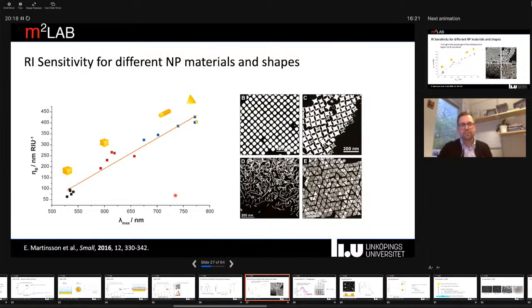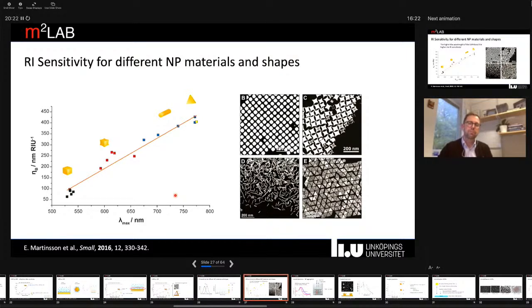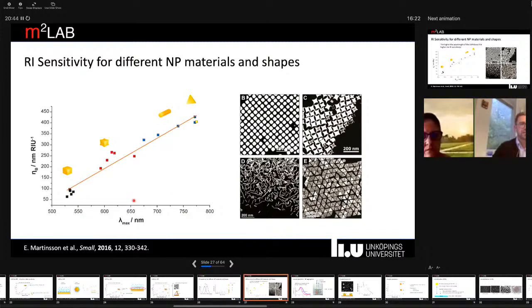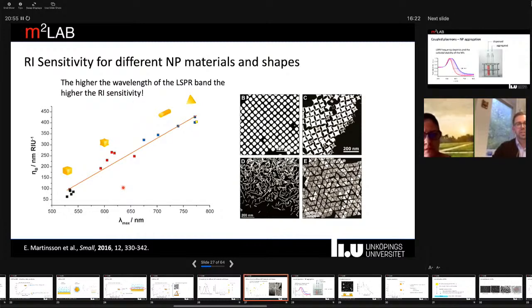But the main reason why we see differences in sensitivity for nanoparticles with different shapes is because they have different positions of the LSPR band. And if you plot the position of the LSPR band, the maximum, as we have done here, against the sensitivity, you see that we can essentially have a straight line here. So there is a direct correlation between the position of the LSPR band and the sensitivity, and the further red the band, the higher the refractive index sensitivity.